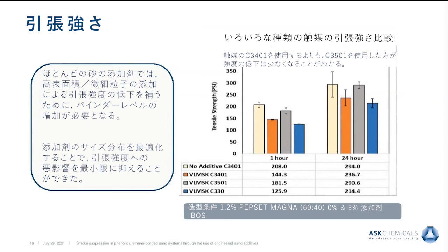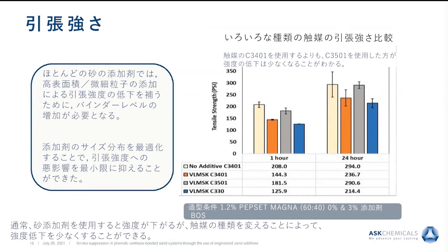So we were very pleased to be able to recover the tensile strength of the core without having to increase the binder level. And I'm saying this because if you think about it, if we had to increase the binder, we would have more like a chicken and egg situation, where more binder, then more smoke, and then more additive, and then reduction of the tensile strength. So we don't want to fall in that cycle. So the idea is that we can recover the tensile strength by just adjusting the catalyst or the type of catalyst. And we also found some catalysts that didn't work very well. So if we do this in some customer or facility, we will have to work closely to determine the most ideal conditions for catalyst and binder to get the best we can obtain.